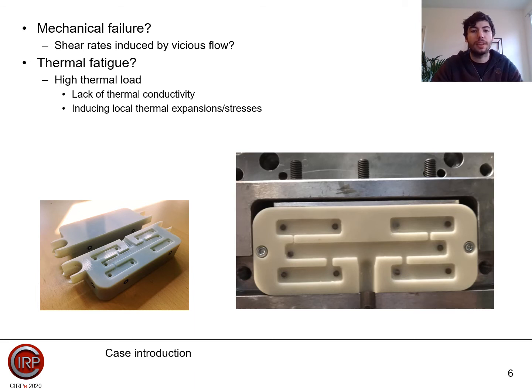Furthermore, it is expected that the lack of thermal conductivity of the material causes large temperature variations within the mold during each shot, inducing thermal stresses in the material. These effects, in combination with a relatively low yield strength of typically used materials, can cause failure of the insert after a low number of cycles, mostly less than 100. Nonetheless, these effects should be fully understood to ensure the reliability of the mold inserts. This paper therefore studies the dependence of shear stresses and temperatures during the injection molding process on the functional life of the mold. Here I've illustrated the design of our case.